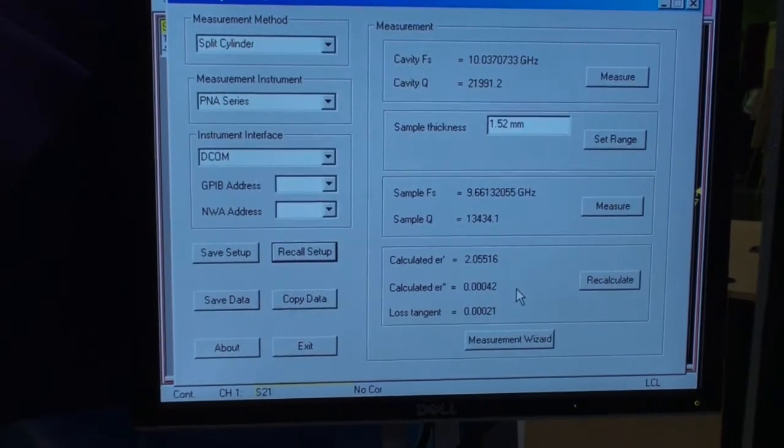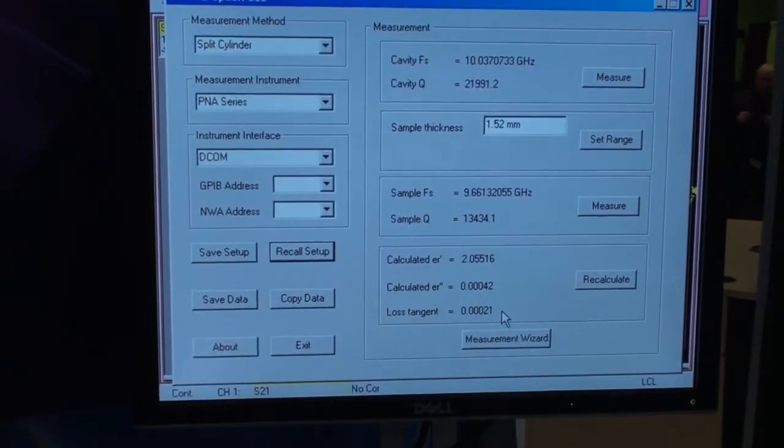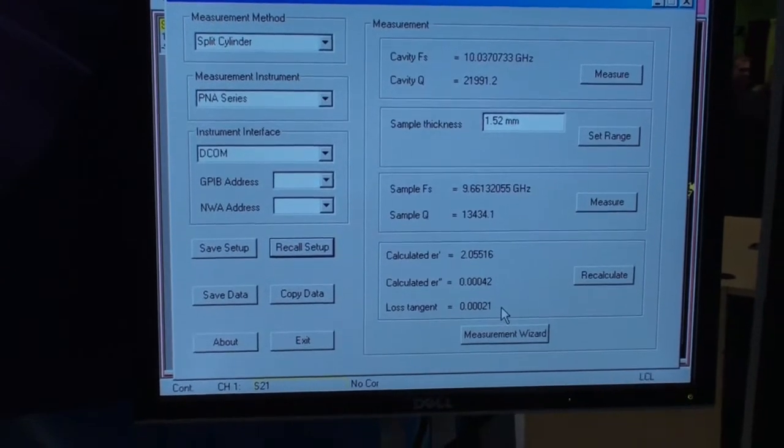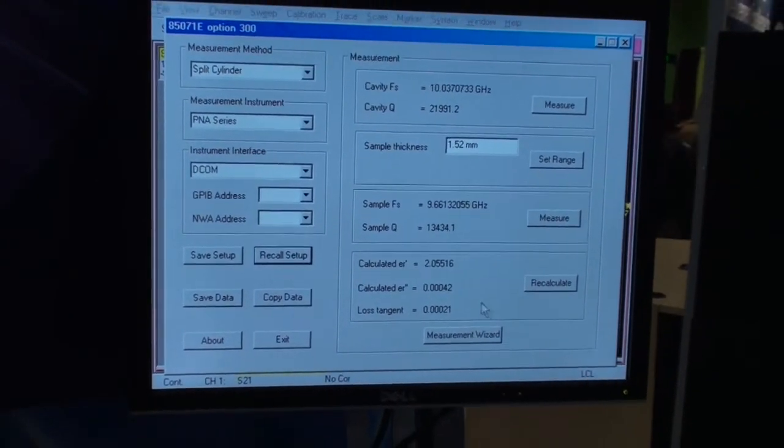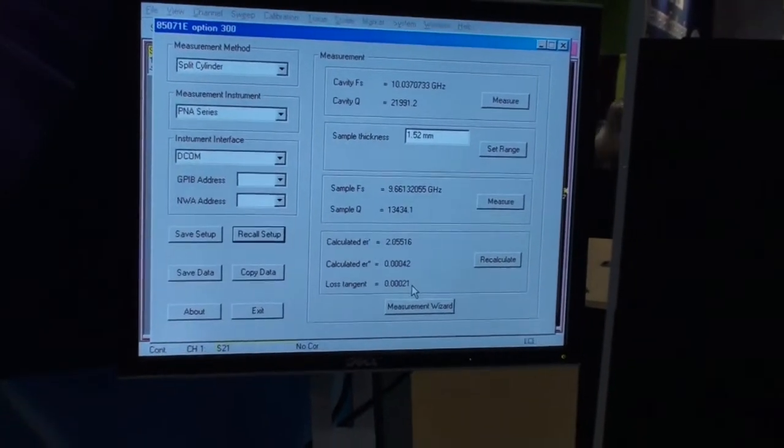the imaginary part at 0.00042 and the loss tangent at 0.00021. And so you can see that we're actually able to get resolution on this loss tangent number of 10 to the minus 4.